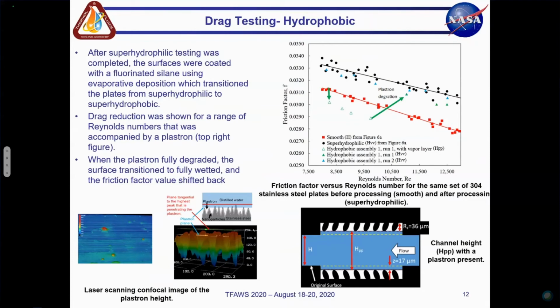So after superhydrophilic testing was done, the surfaces are coated using a fluorinated silane and evaporative deposition to transition these from superhydrophilic to hydrophobic. And drag reduction was shown over the total range of Reynolds numbers where we had this plastron, which was early in the test itself. As you can see in the top right figure, we show drag reduction, and then as the Reynolds numbers increase and as time has increased, you see this plastron degrade